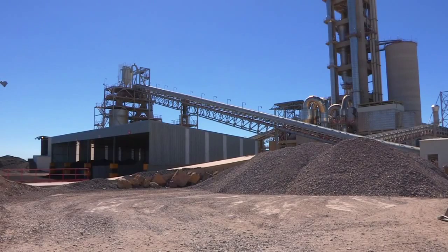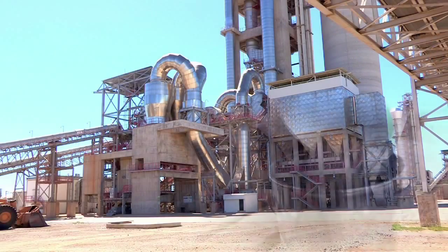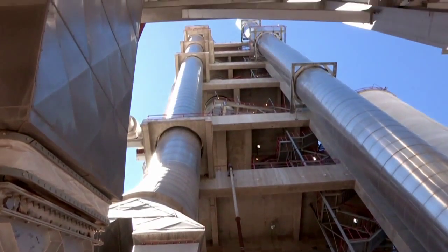Essential additives such as quartz and iron ore are added to the homogenized limestone, shale and marl material, and this mixture is then conveyed to the raw mill, where it is ground to a powder with the consistency of fine flour. Simultaneously, the mixture is dried by means of the redundant heat generated from the firing process. The plant uses roller mills instead of the traditional ball mills. The roller mills save about 30% on the total electrical power consumption compared to traditional ball mills.